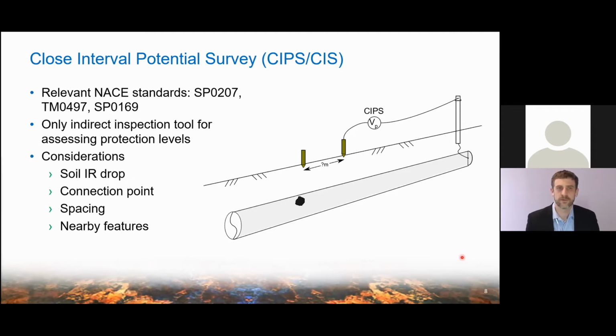Now, a couple of important considerations for a CIPS is the soil IR drop. So if your rectifiers are on, then you're going to have current for sure going, well, hopefully you have current going to all your coating defects. And that we call the soil IR drop. And if that's present, then instead of measuring the true polarized potential, you're measuring an on potential with an unknown error. So we want to eliminate that. And the normal way to do it is to interrupt the rectifiers. And we call that an instant off potential. It has limitations, but it's a pretty normal technique and it's a very powerful technique.